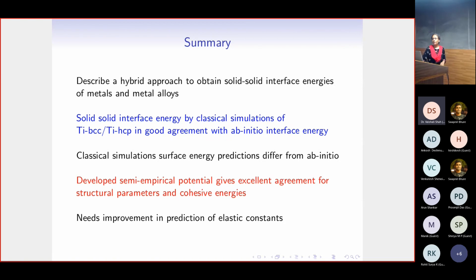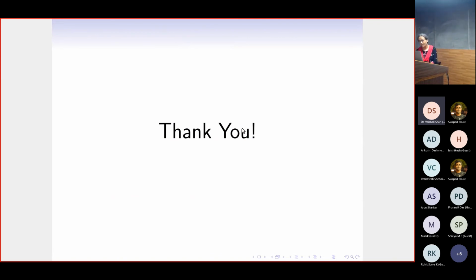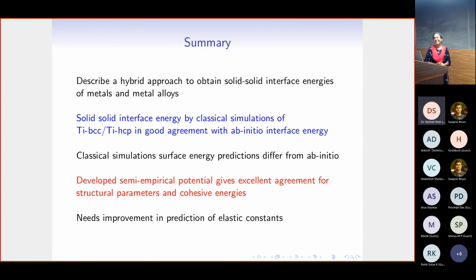We have validated this by doing the ab initio and the classical simulations for the titanium BCC and HCP phases. I'm running ahead of time. We see that the classical surface energy predictions differ from ab initio. So for now, it looks like we'll have to use this combined approach where we determine the surface thicknesses from ab initio and use them in classical simulations to get reliable interface energies. But at some point, it would be nice if we can bypass this step of having to perform ab initio simulations and be able to work directly with classical simulations.